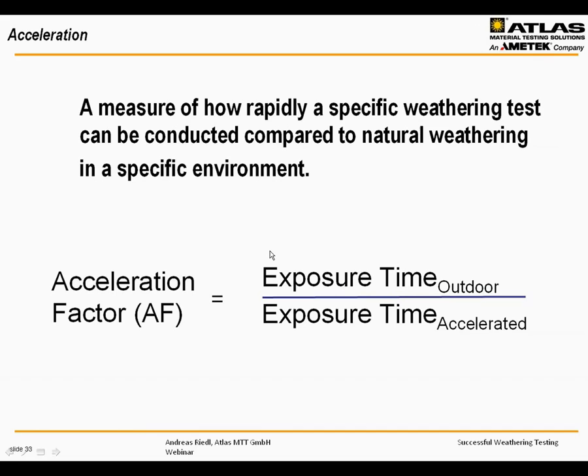The second key characteristic that we looked at before is the acceleration. So you need a fast test. You don't want to wait for years to get a statement about the aging of your material. Of course, there are limits, but you would like to have high acceleration. The acceleration factor is nothing else than the exposure time outdoors divided by the exposure time in an accelerated test, whatever that is, to induce similar changes in properties on replicate specimens. So if you need, for example, for a delta E of 4 or something like that, 12 months outdoors and 1 month in the instrument with a certain specific test procedure, then the acceleration factor is 12, for example.